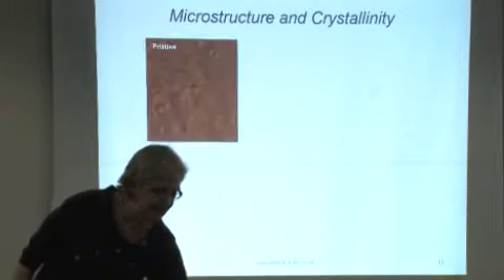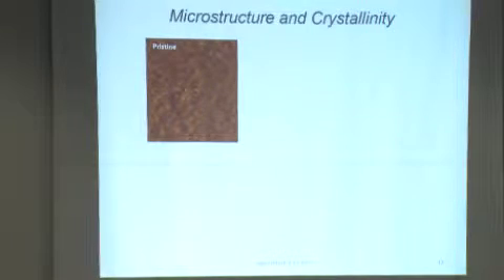All right, if we look at the microstructure and its crystallinity, we start off with an amorphous looking AFM image, and keep in mind that this is strictly a surface image at the air-polymer interface. The interface that is actually important for charge transport is the one at the dielectric-semiconductor interface, which is buried. And we can't really get to that to identify what that structure is, but we can use AFM to look at the surface and sort of infer what may be happening.